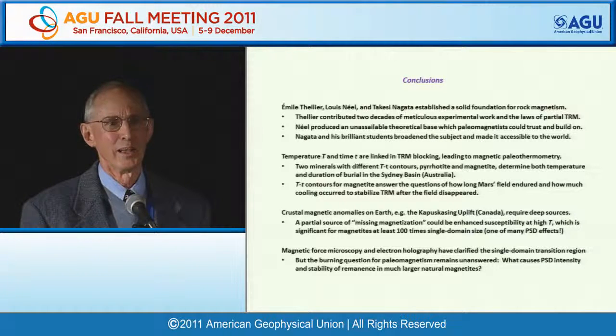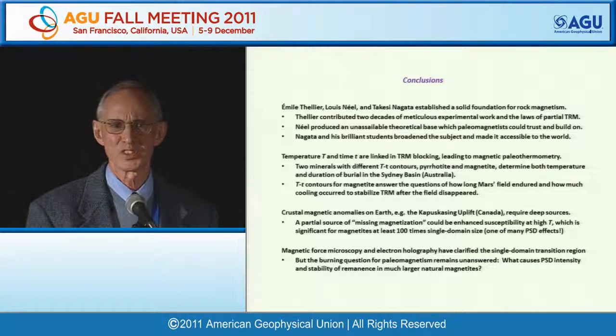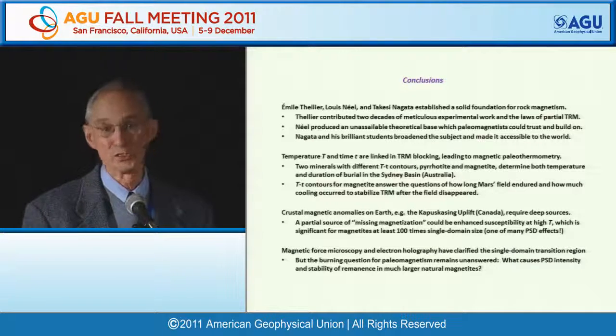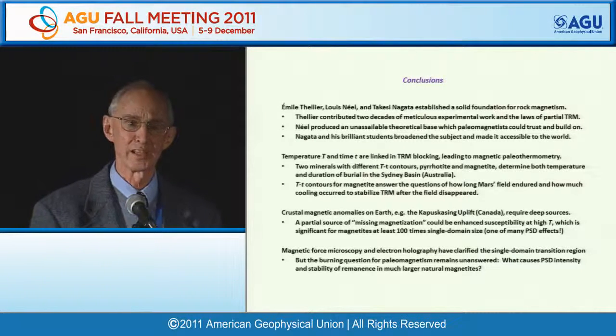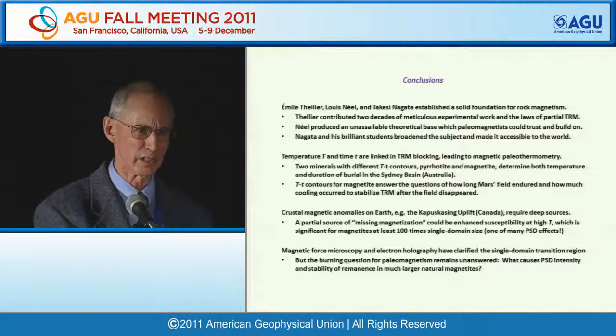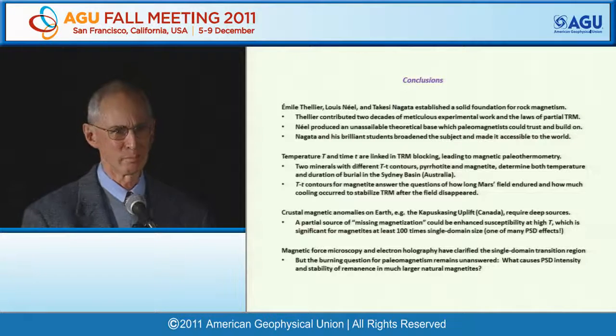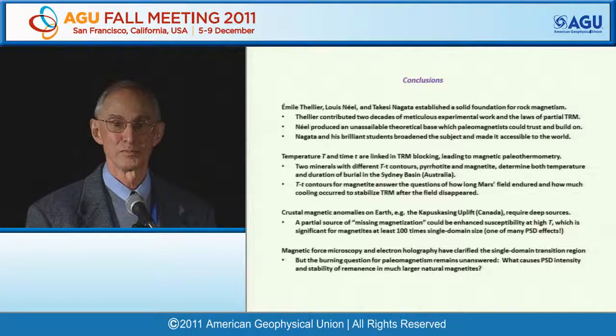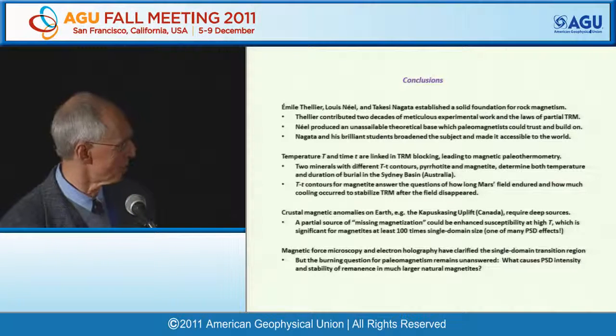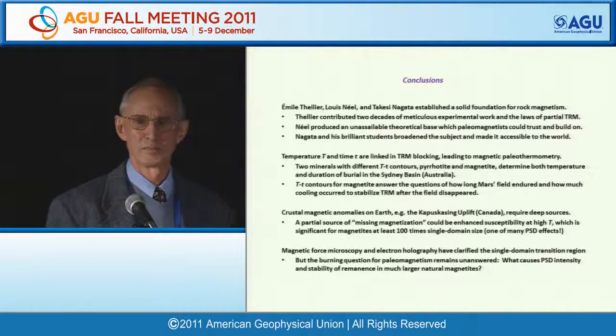But you can produce sort of an ideal magnetization source if you take hematite and then subdivide it on a very fine scale. The layers between these exsolved minerals have remarkable properties. They produce a ferrimagnetism, which is not as strong as magnetite's, but still a substantial fraction of that, coupled with a coercivity, a stability that is very much that of the mineral hematite. Hematite, of course, is weakly magnetic, but strongly coercive. And by conventional wisdom, these things should not produce anomalies. In fact, they do. So I think that's the source that you are referring to. Yes.